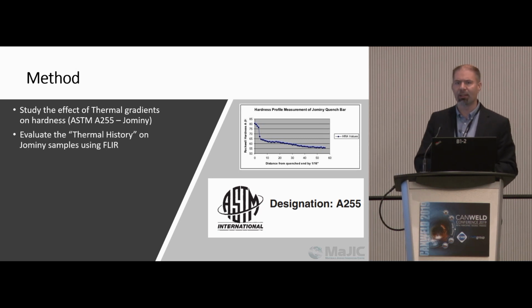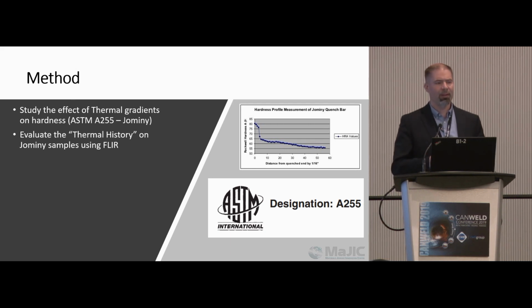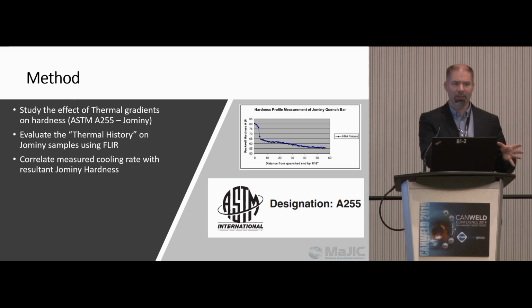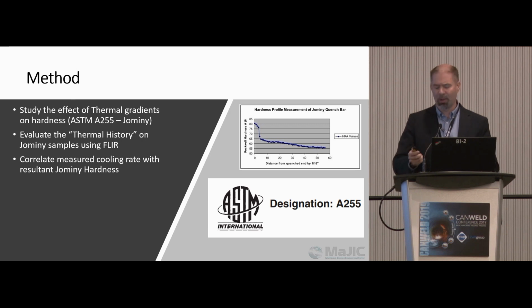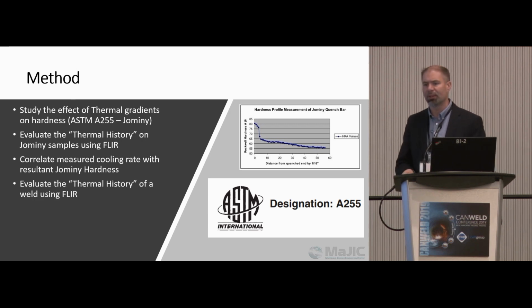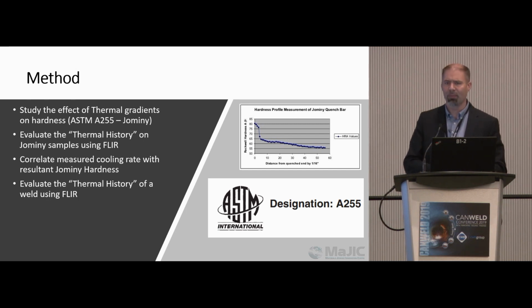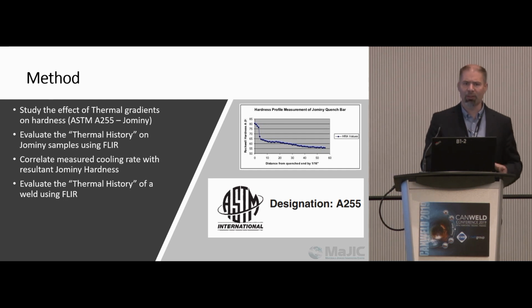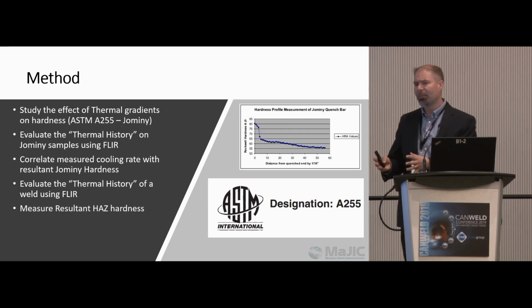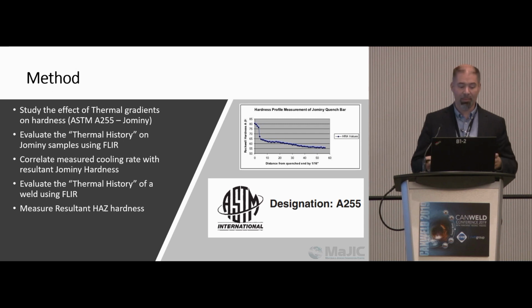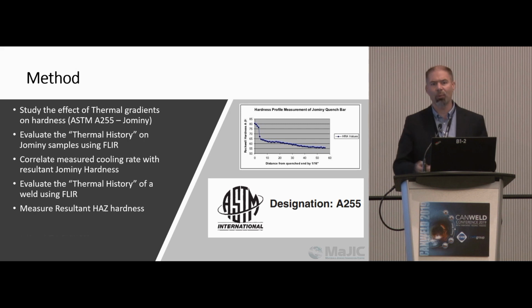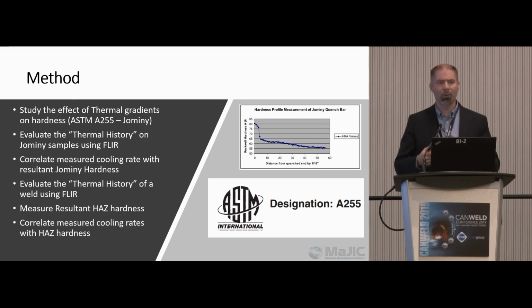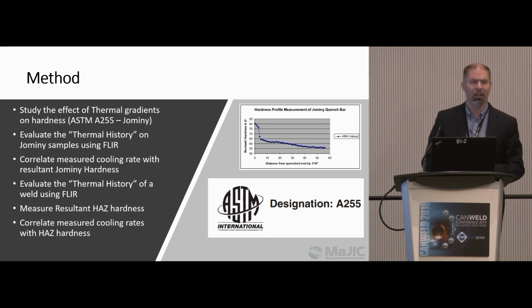and conducting the Jominy end quench. And while we're doing that, we're evaluating the thermal history of the Jominy sample from the oven to the apparatus, the test fixture, and looking at that thermal history along the way. And then we'll take a look at that and then measure the resultant hardness. Straightforward so far. So with that data, we're going to flip over to the welding side and do the same thing, but look at the thermal history of the weld, of the heat affected zone in particular, and then attempt to measure the hardness and then attempt to correlate the data. So can we accurately predict what the cooling rate will result in as a final peak hardness?